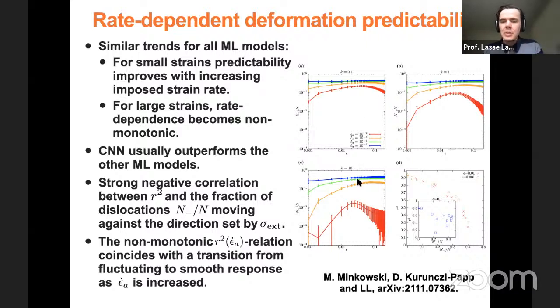and these stiffness parameters. So what we find is that for small strains, we can correlate this R squared and the fraction of dislocations moving against the external stress, which we take to be a measure of the complexity of the dislocation dynamics, in such a way that if almost none of the dislocations move against the external stress, which happens for large rates, then the R parameter, or the predictability, is good. However, if a larger fraction of your dislocations move against the external stress, which typically happens for low strain rates, then your predictability is worse. So there's a nice correlation between the R squared and the fraction of dislocations moving against the external stress.